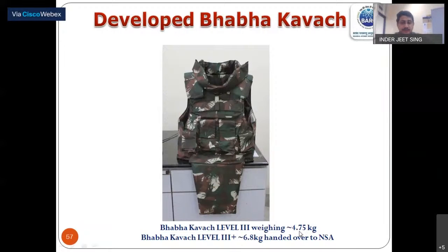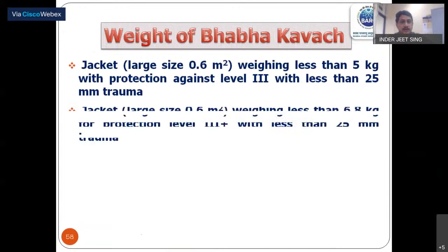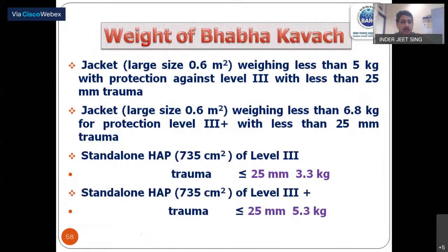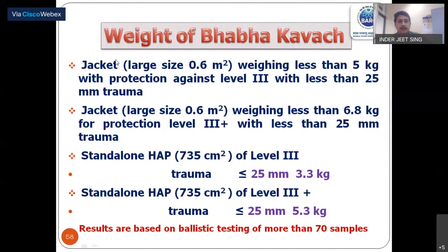Bhabha Kavach has different levels: level 3 weighs 4.75 kg, where the existing one weighed more than 6.5 kg, and level 3 plus weighs 6.8 kg, whereas the existing one weighed more than 11 kg. So here is the summary of how the weight improved. A large size jacket weighs less than 5 kg and gives protection against level 3. Level 3 means protection against AK-47 mild steel core bullets, and level 3 plus means protection against AK-47 hard steel core bullets.